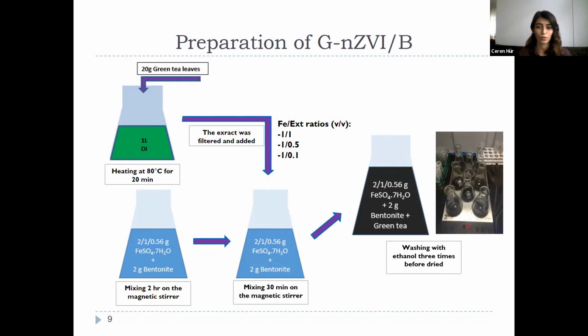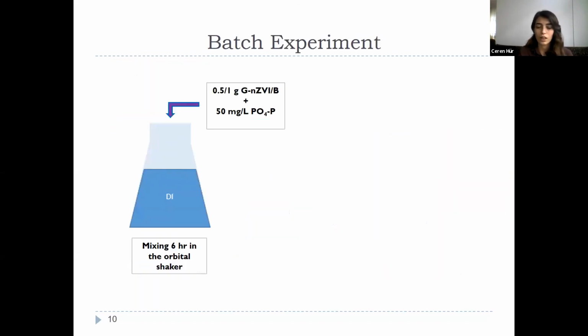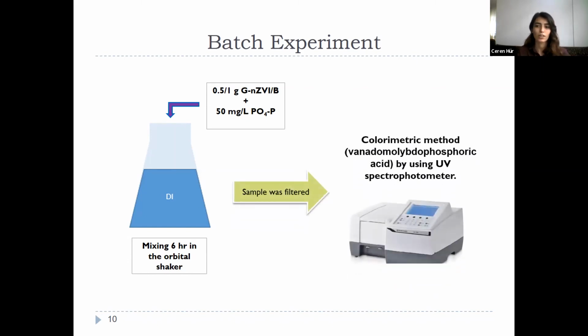The final solution was centrifuged. The composite was washed with ethanol 3 times for removal of excess amount of iron or green tea extract. After that, the composite was dried, crushed and prepared for experiment. In batch experiment, half or 1 gram of nanocomposite, G is green synthesis, B is bentonite, and 50 milligram per liter phosphate were added into the DI water and mixed for 6 hours in orbital shaker at room temperature, and then the sample was filtered and final concentration was measured by colorimetric methods.